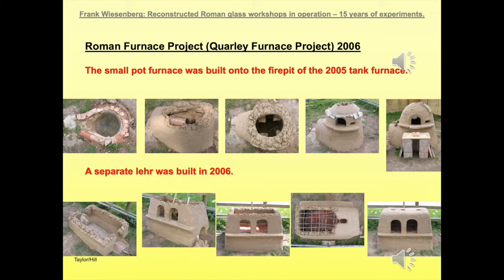The unsuccessful tank furnace was taken down for the 2006 project, and Mark Taylor and David Hill erected a small pot furnace on top of the fire pit of the old tank furnace. In the middle picture on the first row, you can see a couple of Roman roof tile fragments protruding from the side walls. They served as a support for the glass pot, the melting crucible, held in a central position inside this furnace. As a replacement for the annealing chamber, which was placed aside from the tank furnace in the 2005 project, Mark Taylor and David Hill decided to build a separate lehr in 2006, which was powered through two stokehole openings from the sides, and featured two doors to place the vessels inside the vessel room.